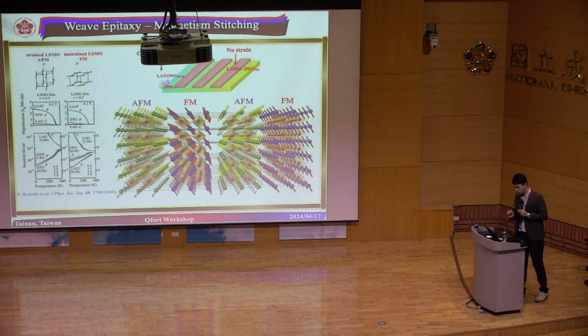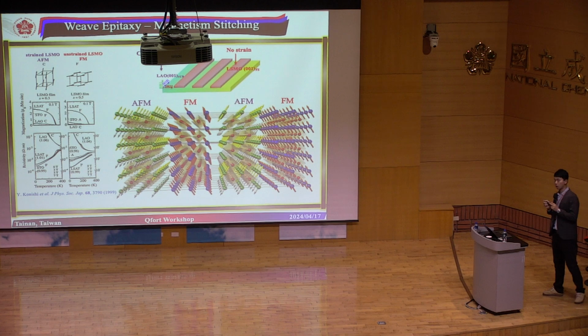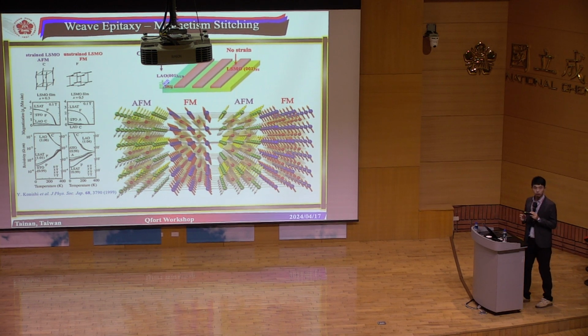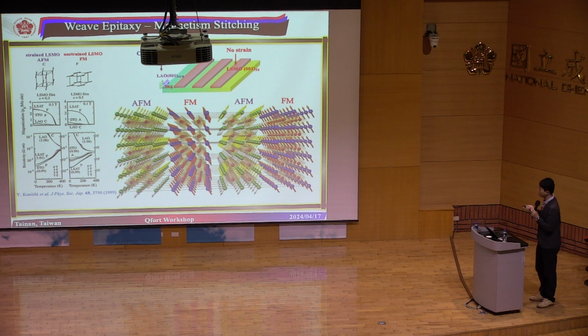Okay, so let's move to the next capability that we can essentially achieve. If you look at the phase diagram for the LSMO, if you do nothing to it and cool it down, it's a ferromagnetic phase. But if you apply a strong compressive strain, once it's compressively strained, it will become an anti-ferromagnetic material.